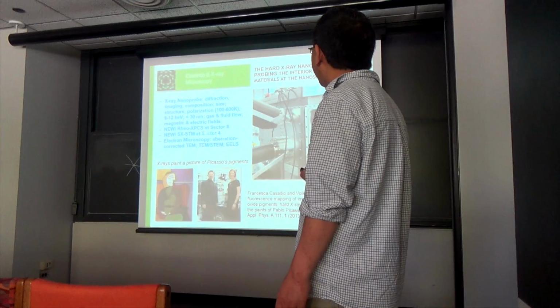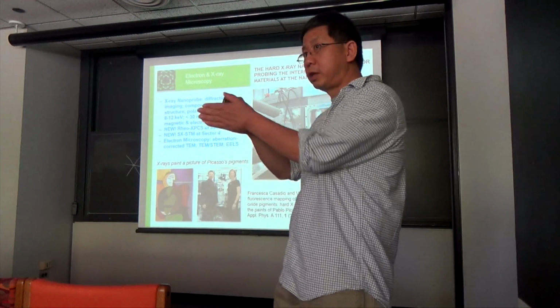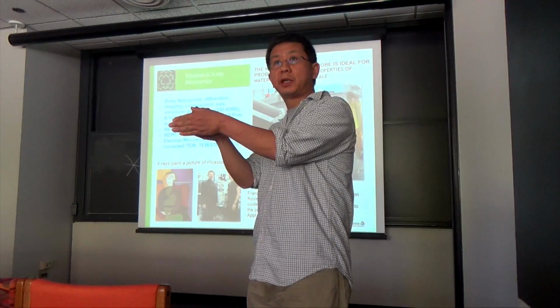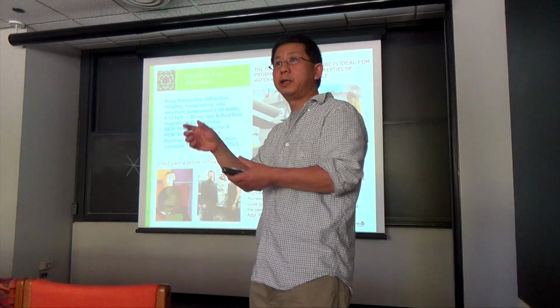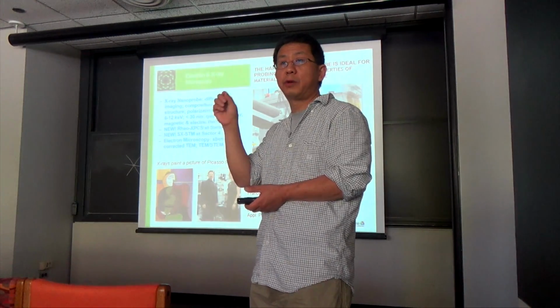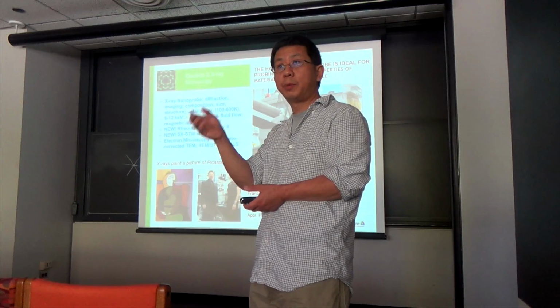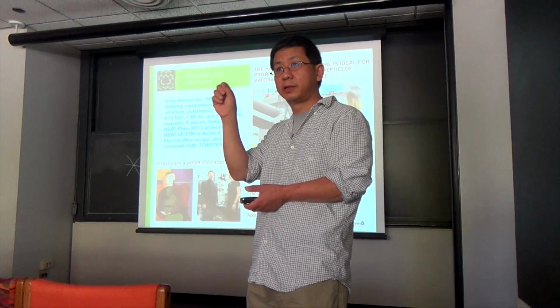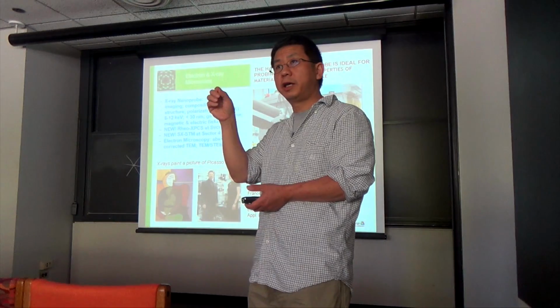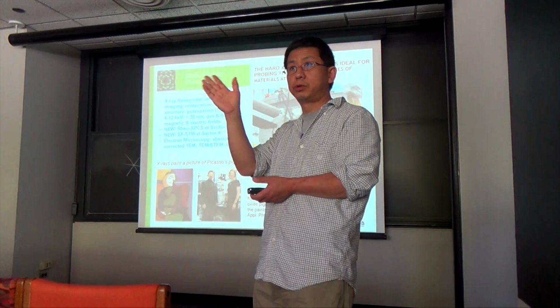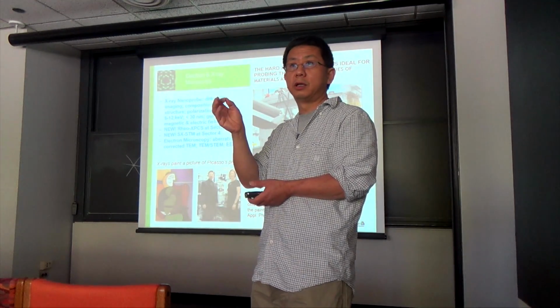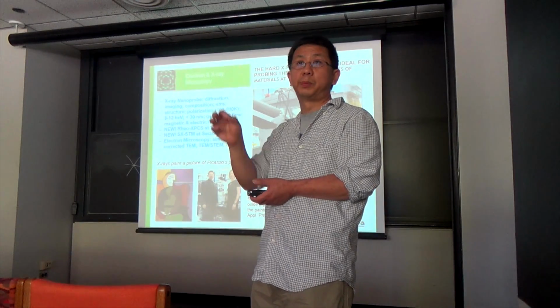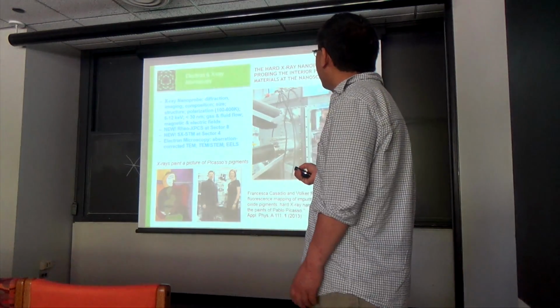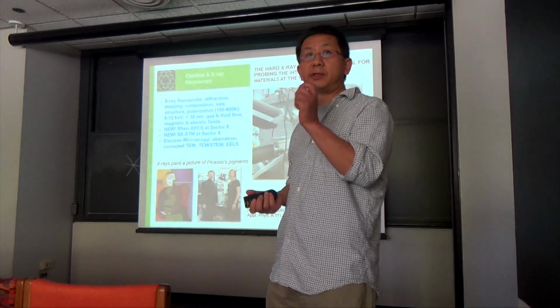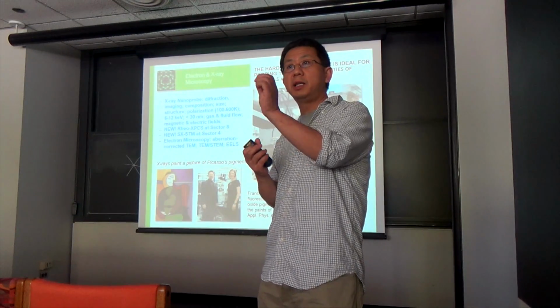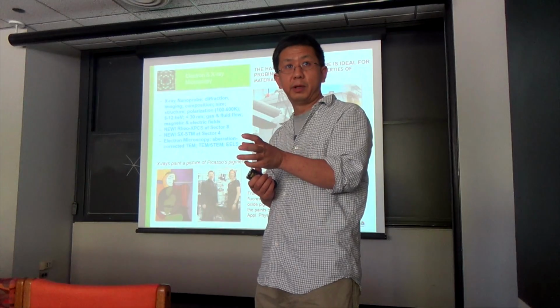And so what they do is that they focus the X-ray, they scan the X-ray beam on the surface of your sample, and then they look at X-ray fluorescence. X-ray fluorescence can tell you the chemical composition locally on that spot, right? And they can also look at X-ray diffraction that tells you crystal structures at that local spot, right? So what they do very well is chemical sensitivity to a very tiny amount of material. They can pick it up, right?